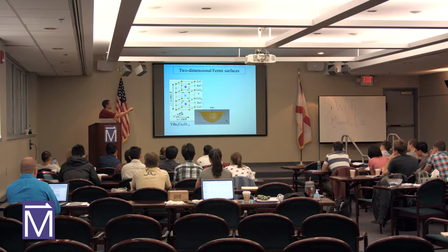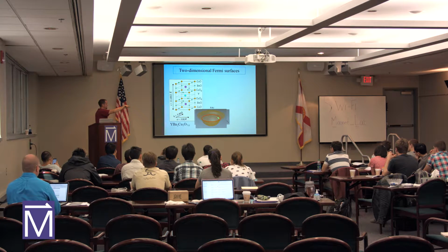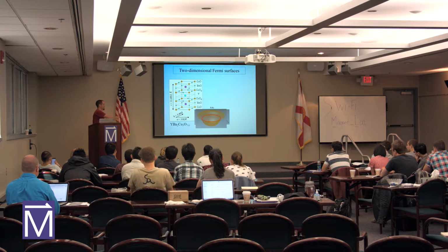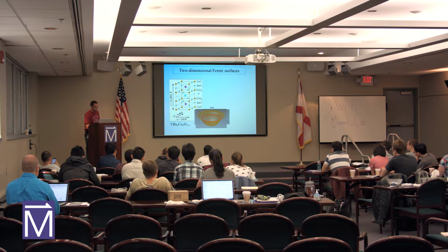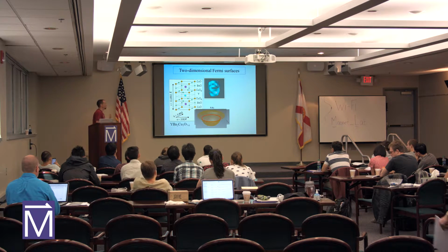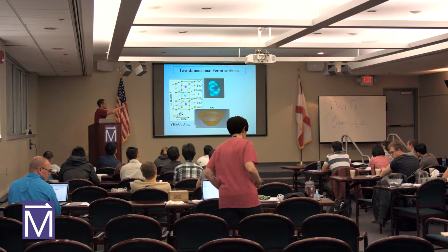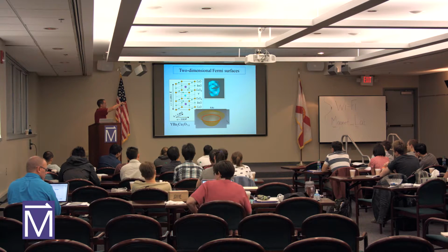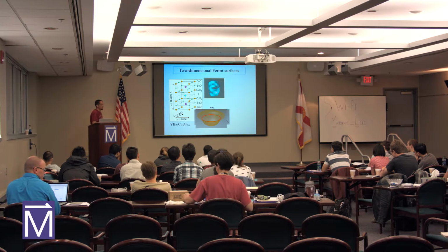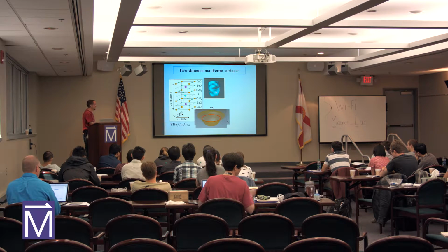If we had the same thing in the x and y direction, then we can have a circular sort of energy relationship, and this would be the path of the carriers. If it's isotropic vertically along the z-axis, we'd end up having a perfect cylinder. Okay, a circular shape, make it grow vertically, a perfect cylinder, but most of the time nature gives us kind of a warped or stranger shape. Okay, so this is our 2-dimensional cylinder, a 2-dimensional Fermi surface, and this is the pathway of the carriers around the edge of it.